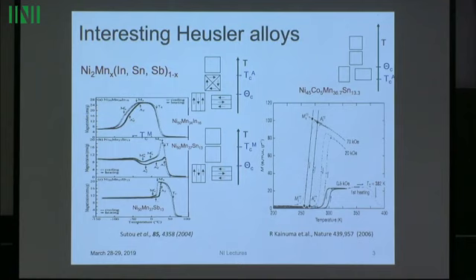What's happening here is that the Curie point of the austenite phase is below the transformation temperature of the austenite-martensite phase transformation. So of course, if you could somehow stabilize the austenite to lower temperatures, you would see it ferromagnetically ordered, but you don't see it ferromagnetically ordered because it transforms already to martensite.